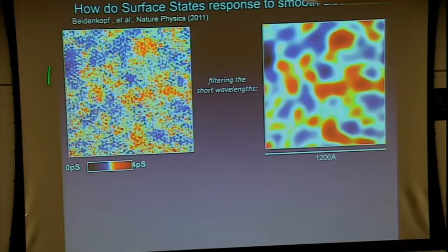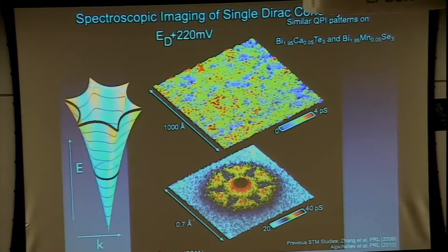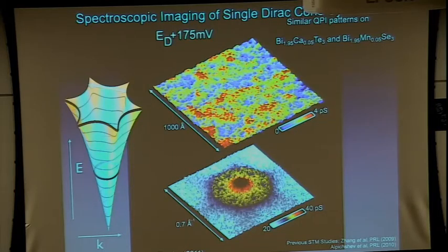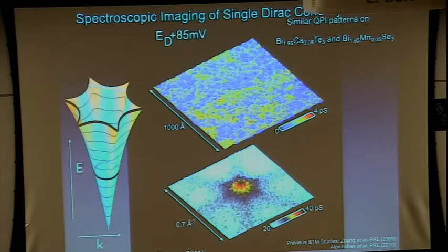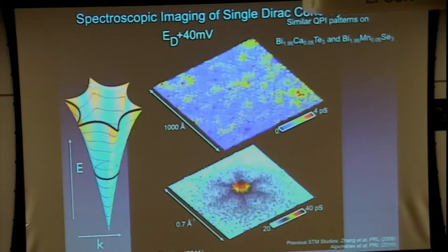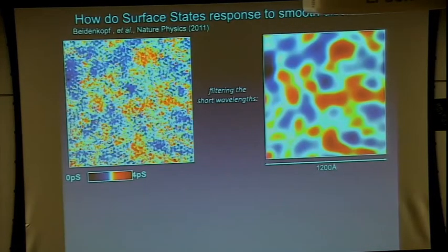these pictures that we were Fourier transforming, right? And what we found in this picture is that if you go down and look at the electron waves as you get very close to the Dirac point, you can see these puddling things going on here. Okay? Essentially, your chemical potential in these samples is varying as a function of position. Sure, we can make samples that are better and better, and we have really improved the quality of these samples over the last 10 years. But this is what defects do to any semiconductor. Essentially, you will create some background potential, which is your Coulomb potential,